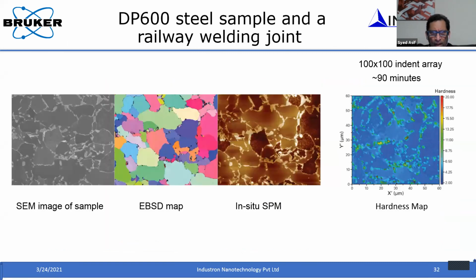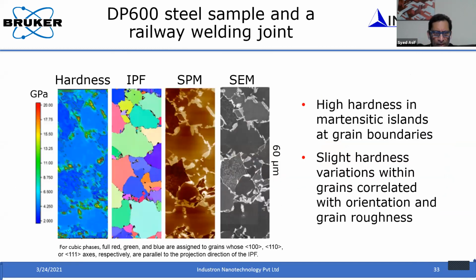Okay. Another example, this is again a railway welding joint. The first image I'm showing is an SEM image, and the next one is the EBSD map. The color of the map shows the crystallographic orientation. At the boundary, you can see the dark, black ones; basically they're all martensites. The next image is the in situ SPM image that you can get with the instrument, and then the next image is the hardness map. If you look at it in close up, you can see that at the grain boundaries you have these martensitic islands, and the hardness is pretty high at the grain boundaries.